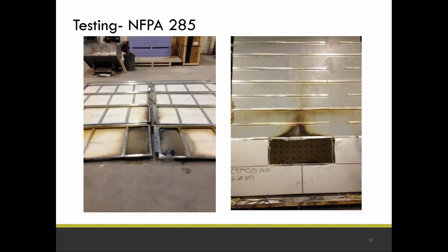This is the same wall that's been taken down. As you see, we lost the front panels down here. As you look back here, this particular wall didn't have insulation in it. That was considered a worst case at that time. And you can see we burned a little bit of the air water barrier, but nothing but a little bit of char.